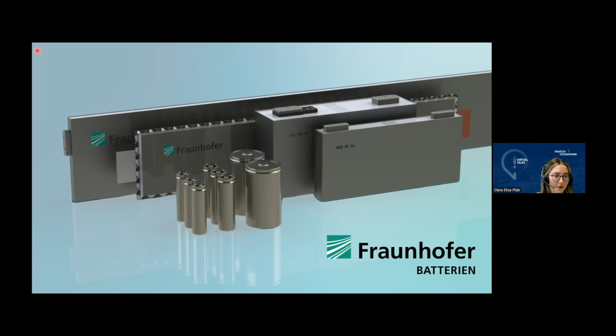And then another question, how important is the pore structure inside active materials? Very important, I would say, because these electrochemical reactions take place at the interface between electrolyte and solid phase. And the more pores you have, the more surface, the faster the material would react, and the less the lithium from the electrolyte would be depleted. So the pore structure is very important.